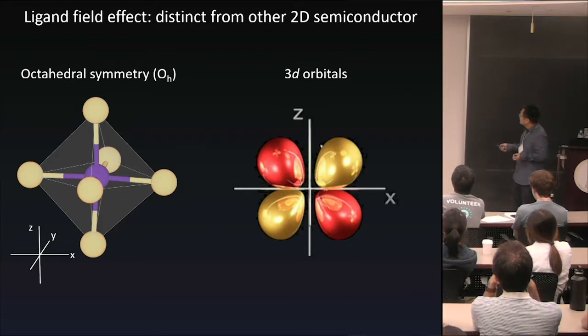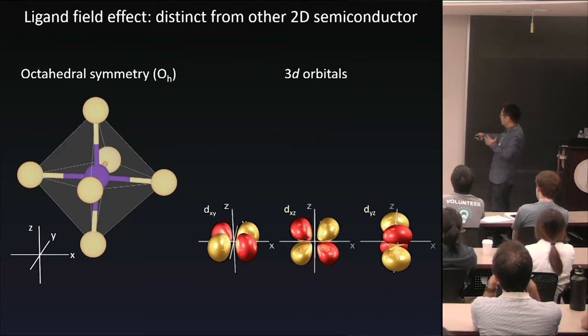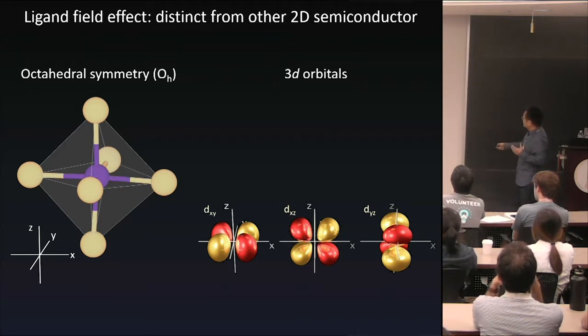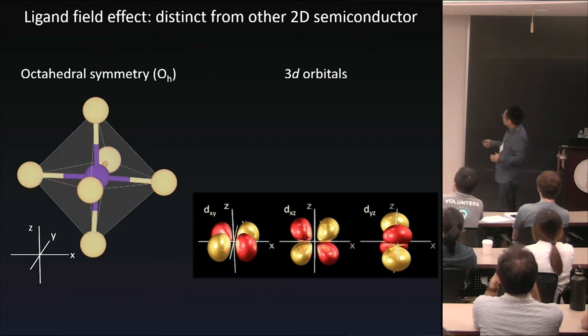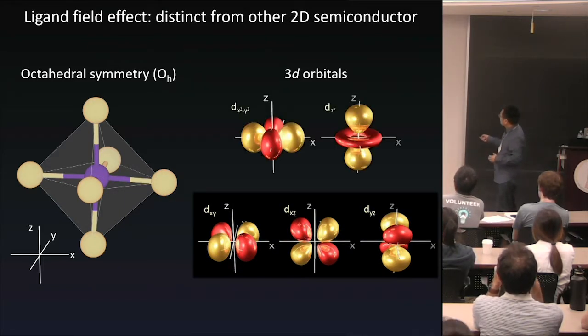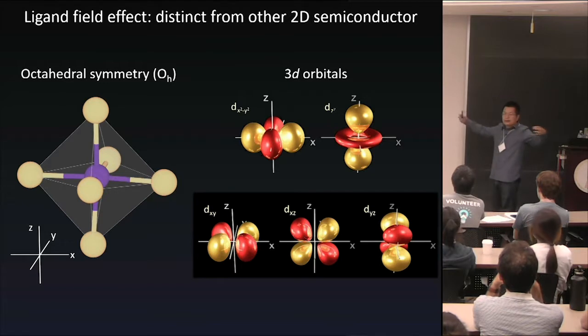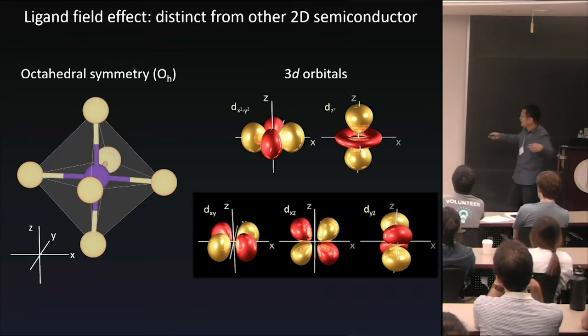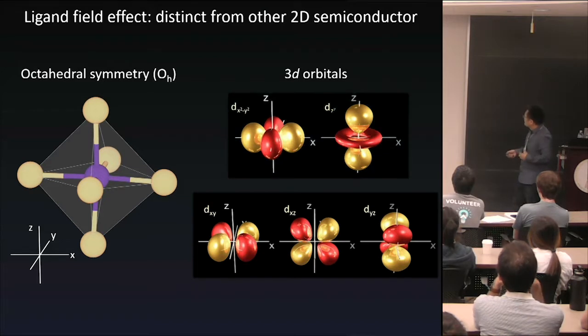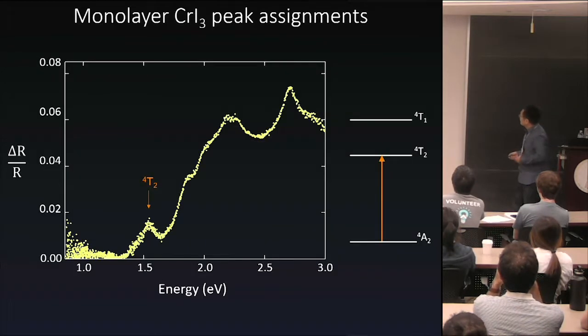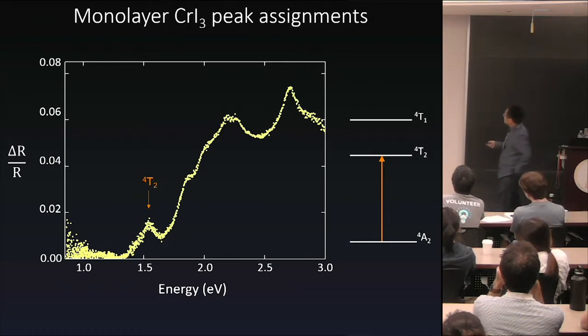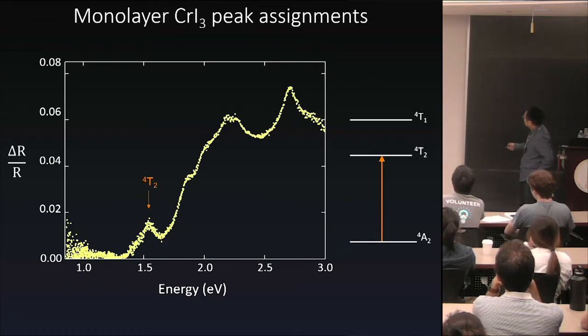Because it's a Ligand field for chromium with 3D orbitals, the physical property is determined by the orientation of these orbitals I show you here. For example, there are 5 of them: dxy, dxz, dyz. If you study group theory, you will know what I'm talking about, right? All these angles are important. And there are another 2, which are symmetric, this one. It depends on the angle of these orbitals, then they can talk differently to these outer atoms. Then there will be different mixtures of these orbitals. I won't go into all the details, but the short summary is that the transitions we care about are from these 3.